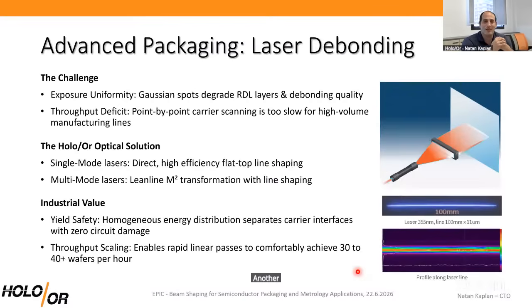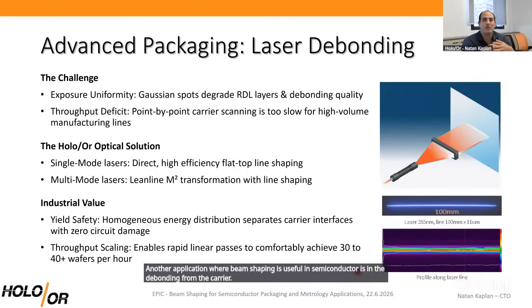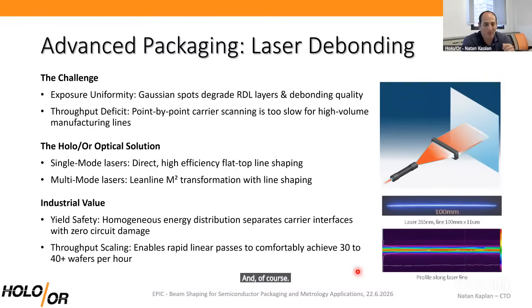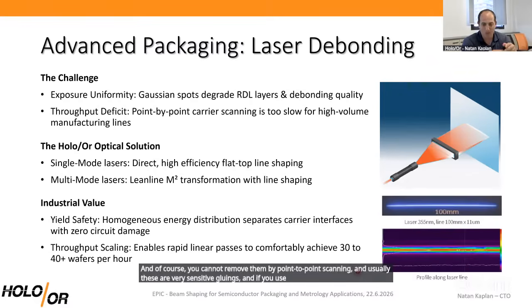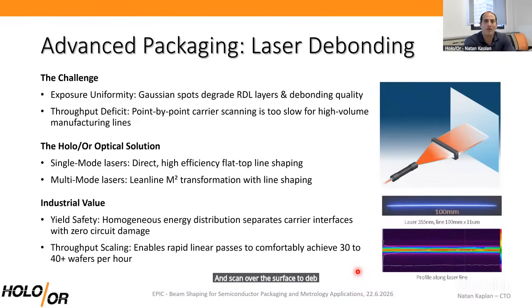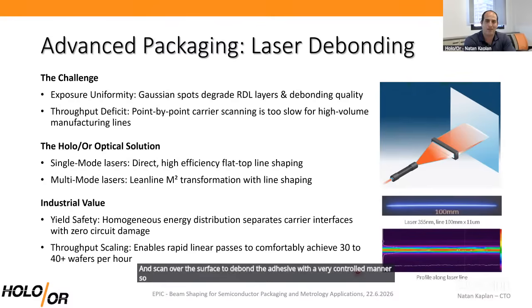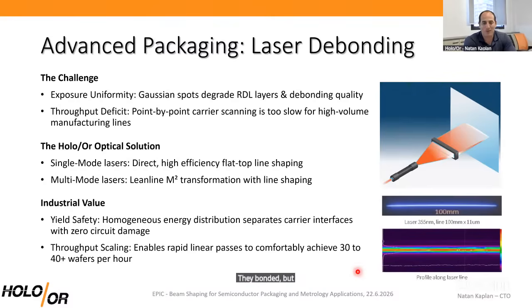Another application where beam shaping is useful in semiconductor is in the debonding from the carrier. Now, you have a lot of very thin layers during semiconductor production, which are glued to a carrier wafer or base plate. And of course, you cannot remove them by point-to-point scanning. Usually, these are very sensitive gluings, and if you use too much energy, you go into the active layer and you destroy devices. So there are two families of solutions, but in both types, you need to generate a line scan with very good uniformity and scan over the surface to debond the adhesive in a very controlled manner so that everything is debonded, but you do not go into the active layer.